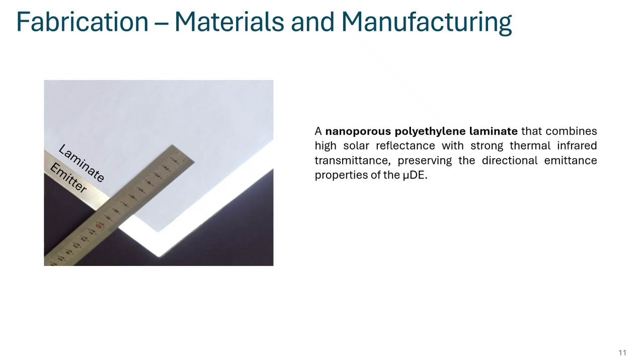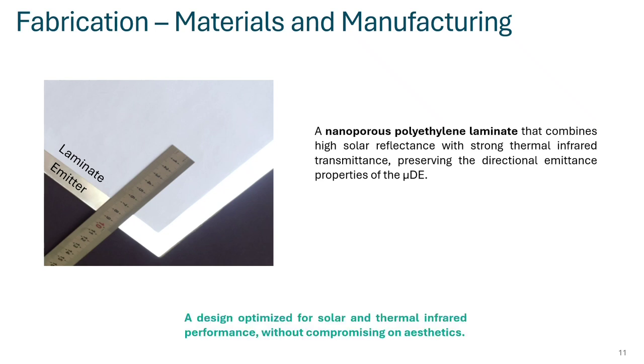For these reasons, we add a white nanoporous polyethylene laminate on top, as you can see here. And the nice characteristic of this laminate is that it combines strong solar reflectance with high thermal infrared transmittance. And then, we solve both the aesthetic and solar issues, but we also preserve the directional emittance in the infrared. Altogether, we propose a design optimized both in the solar and thermal infrared ranges without compromising on aesthetics.